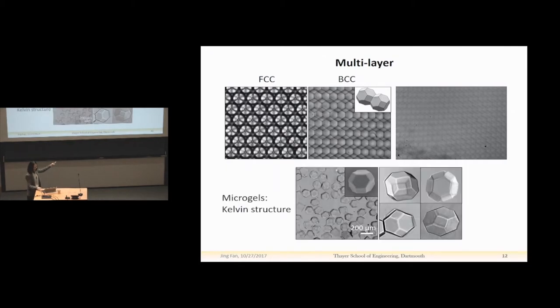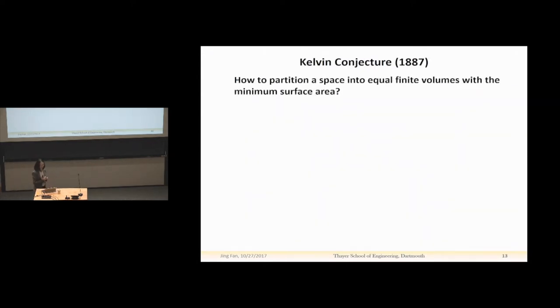And if we solidify the deformed drops at this state, we can get these shaped microgel particles. They are truncated octahedra. And actually they have another name, the Kelvin structure. And why is that? It's because of a conjecture proposed by Lord Kelvin in 1887. He asked this question: how to partition space into equal volumes with the minimum surface area? So maybe it's easier to think about the 2D version of this problem: how to partition an infinite plane into equal finite areas with the minimum peripheral length.